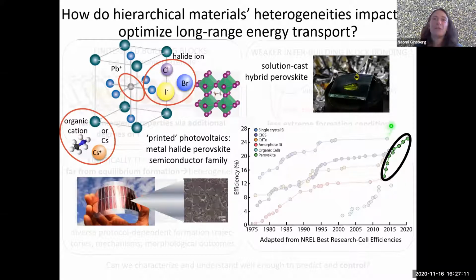So generally, the films that are formed in this way are polycrystalline. So a natural question is how the grain boundaries or other heterogeneities impact photogenerated charge transport. So just as an example, which of these sorts of trajectories here is the most likely or most desirable? And how would you actually make those two things match? Experimentally, this is very challenging to measure, because the carriers travel on ultra-fast timescales, and in suboptimal materials at least, may travel only distances much smaller than that of the optical diffraction limit.